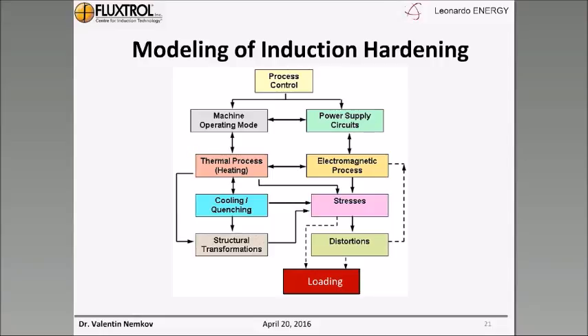Then we can simulate the structural transformation that happens in the process of heating and quenching. And then stresses caused by the electromagnetic process, by thermal expansion, and by quenching structural transformations. All these factors create stresses varying in time. And at the end of hardening, we have residual stresses in the part and some distortions.